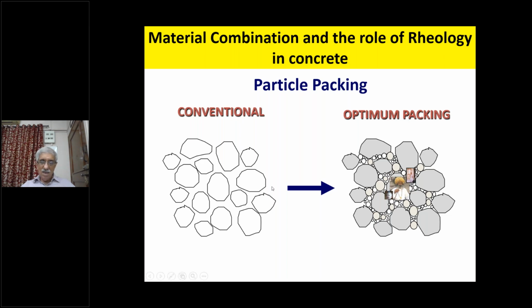packing the cementitious material. So when you pack between the cement particles, the cementitious material, after the complete hydration process is completed, there is hardly any water within the cement particles, and the whole thing has been transformed into a solid material. So if you have such a gel made and it packs the aggregates properly, you get high performance concrete.